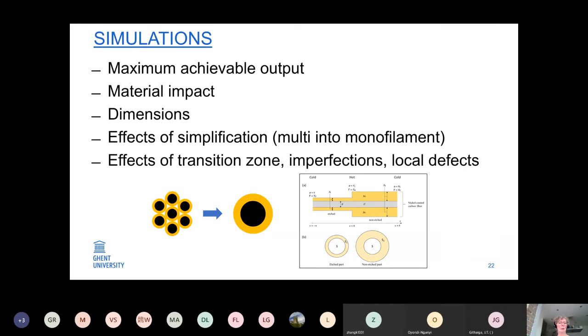And then also effects of the transition zone. You always have a transition between the carbon and nickel coated carbon. In an ideal case, this is 100% sharp, and there is no nickel in the intermediate layers. But with the modeling, we can estimate what would be the effect if this is not the case. Also, the effect of imperfections and local defects and inhomogeneous areas are to be included.